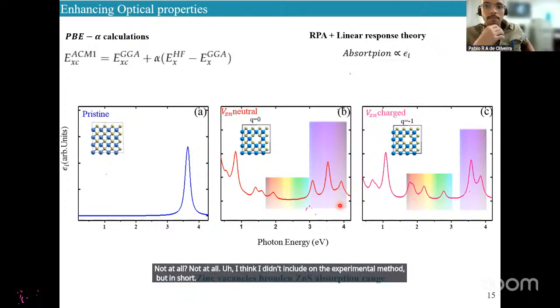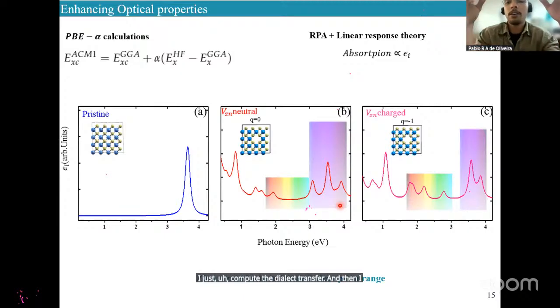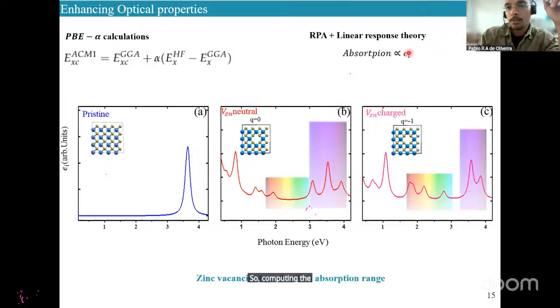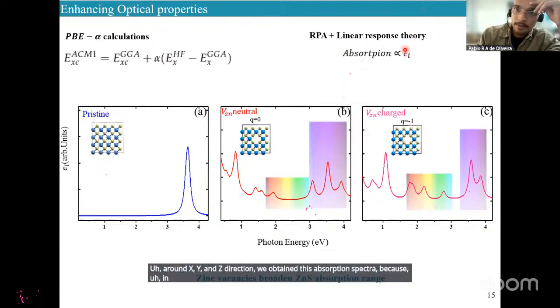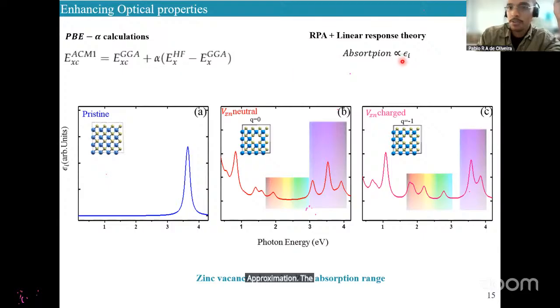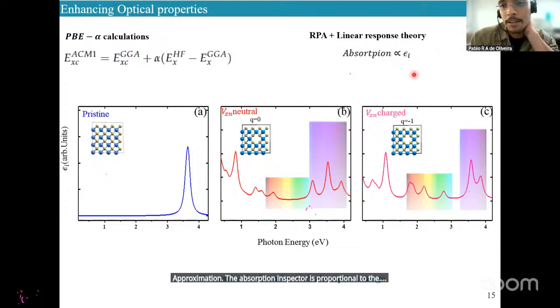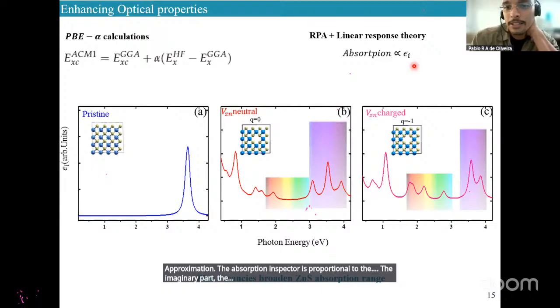I think I didn't include it in the methods, but in short, I just computed the dielectric tensor, and then I considered the absorption to be the same in all directions. So computing the modulus of the average of the dielectric tensor along the X, Y, and Z directions, I obtained this absorption spectra, because in this approximation, the absorption spectra is proportional to the imaginary part of the dielectric tensor.